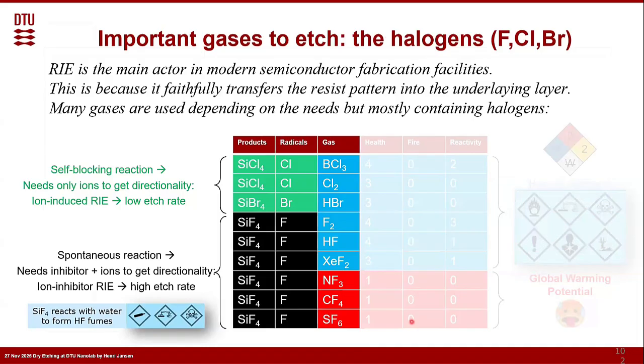So reactive ion etching is the main actor in modern semiconductor fabrication facilities. This is because, as we just saw, it faithfully transfers the resist pattern into the underlying layer. Many gases are used depending on the needs, but mostly containing the halogens, like BCl3, Cl2, F2, etc. As we talked about, the chlorine and bromine based plasmas create the radicals we need, but it is a self-blocking reaction. So it really needs to catch the backbone, and it needs ions to get directionality. Therefore I would call it ion induced: low etch rate, but straight.